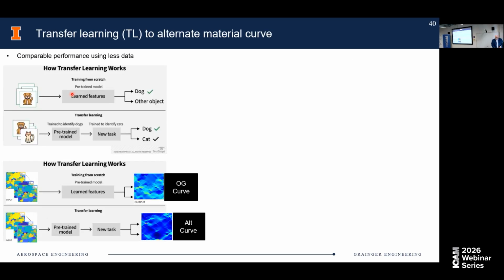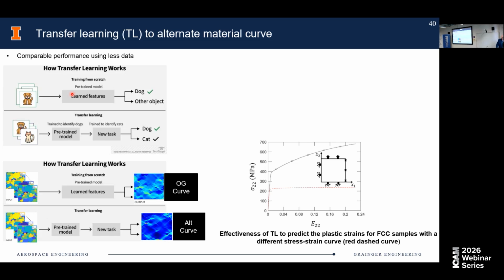And now, and this will be the last thing to show: transfer learning. Can we use this for a different material? And this is the way that we envision bringing experiments into this, right? Because experiments will have a very limited number of data points, right? This is kind of the key thing. So can we use the existing network to predict a different response, let's say, this red stress strain curve? Now, it's still an FCC material. You could do transfer learning on different crystal structures. That's a bit more difficult. We've done a little bit of that.